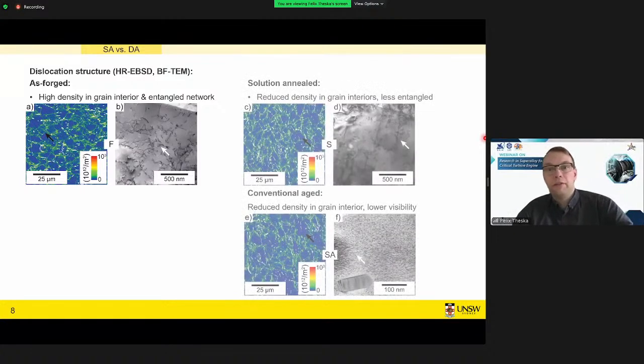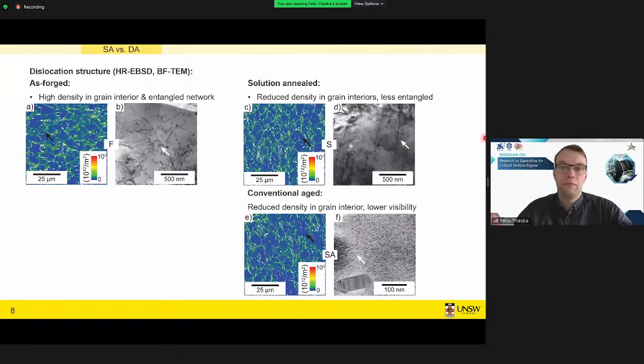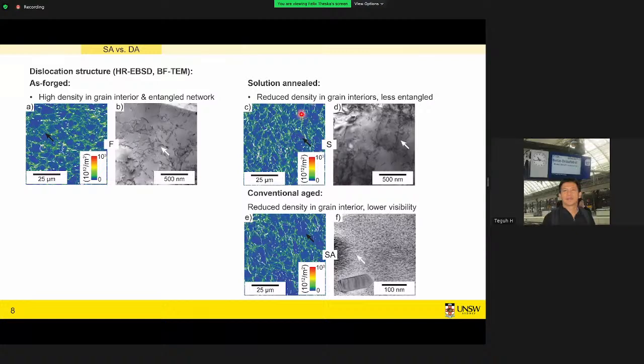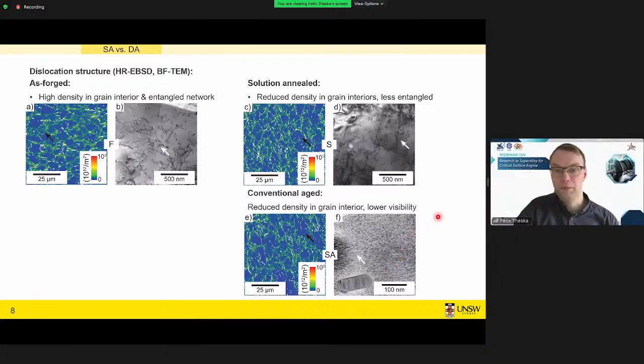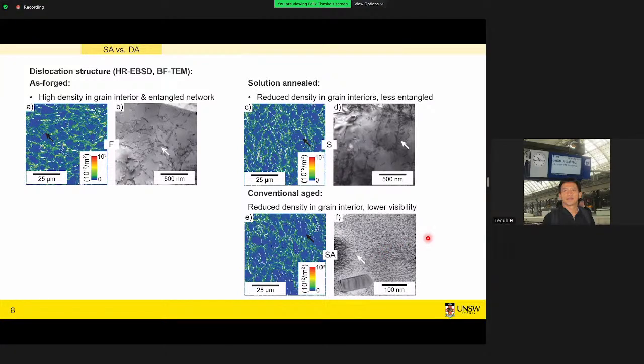If we follow the conventional processing, that means solution annealing and then aging, we find that after solution annealing, dislocations are still there, but we find less of them, and the grain interiors become mostly free of dislocations. And even after aging, now we have these precipitates overlaying in the contrast, so it's very hard to find any dislocation structures at all. We compare this to the direct aging.